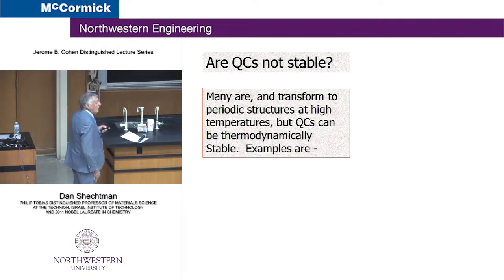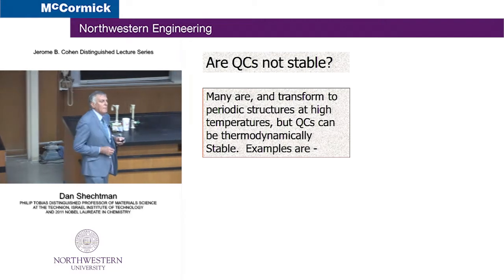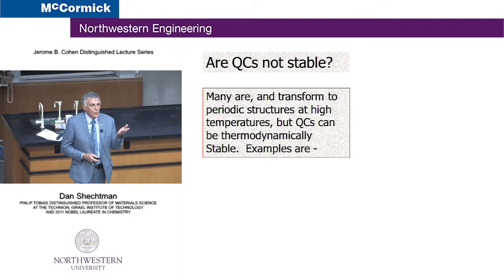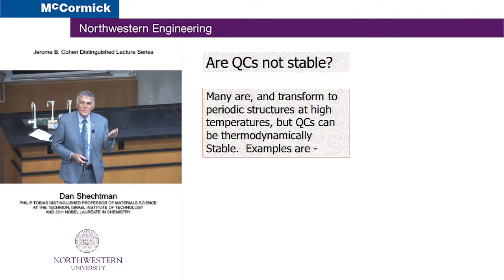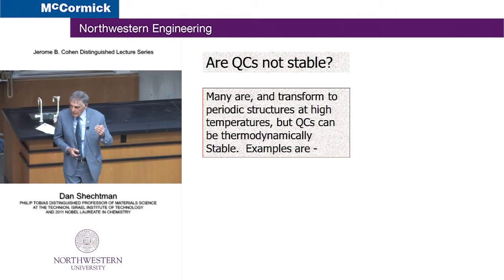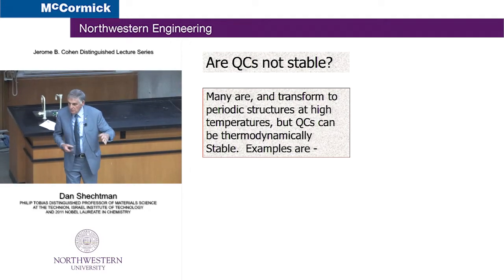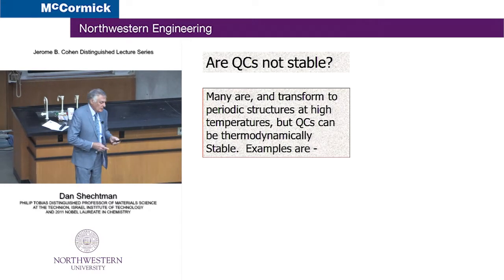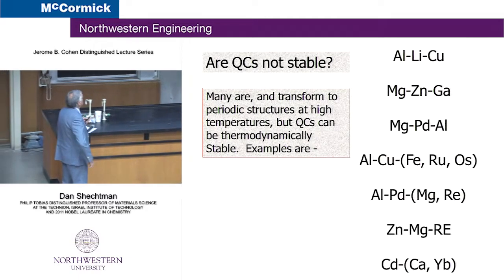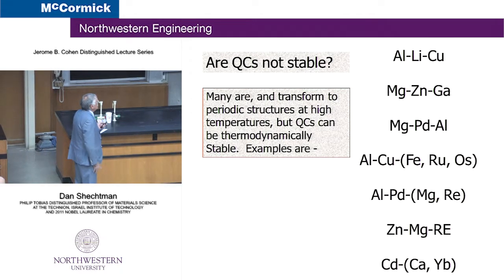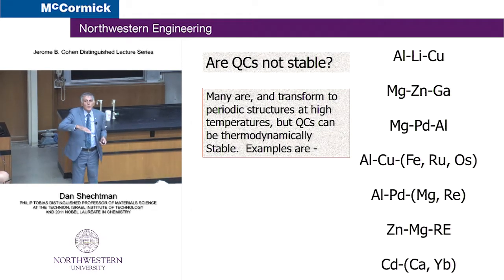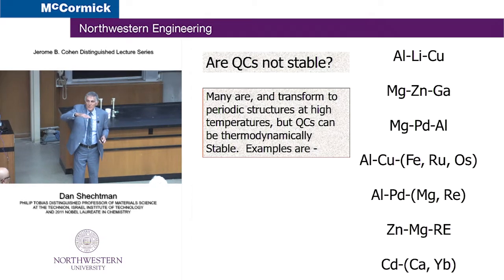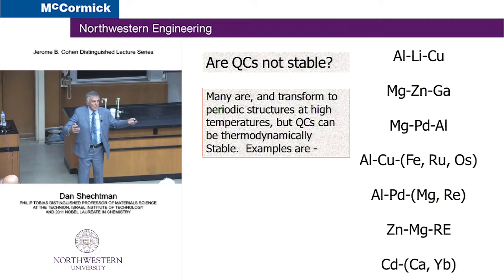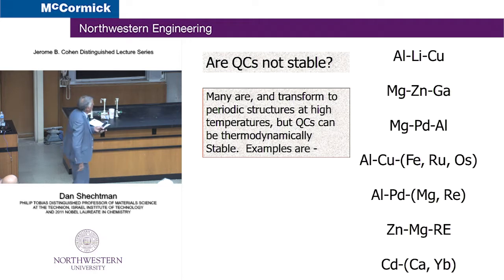Are they not stable? Well, many are not stable. What does it mean? It means that when you heat them up to about 400 degrees C, they will transform to a periodic phase. But below that temperature, they are stable, quasi-periodic. And there are many who are stable. Stable means that if you heat them up, they melt congruently. They melt without any phase transformation in the solid phase, right? In the solid state. So there are many stable ones. This is not the reason they were not discovered before me.